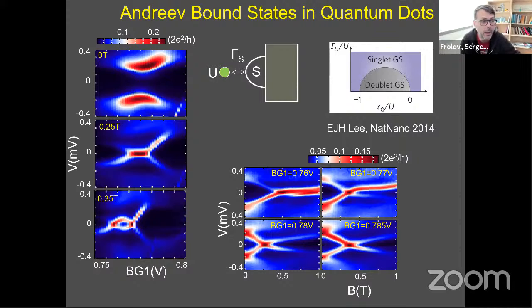So here's an example from our lab, but the diagram is from this paper that first studied Andreev bound states in quantum dots as a function of magnetic field, right? Magnetic field is important for Majorana. So the physics of it is basically the Anderson impurity model. So you have a lead, which is in this case superconducting, and it's coupled by some rate to a dot, which can have a spin on it. And you study the screening of the spin by the lead, and the parameters are on-site energy and coupling rate, and you can see all that represented in this diagram.